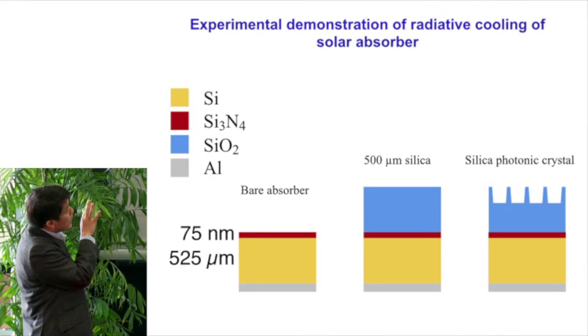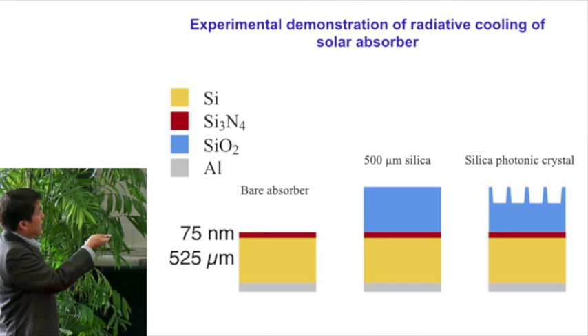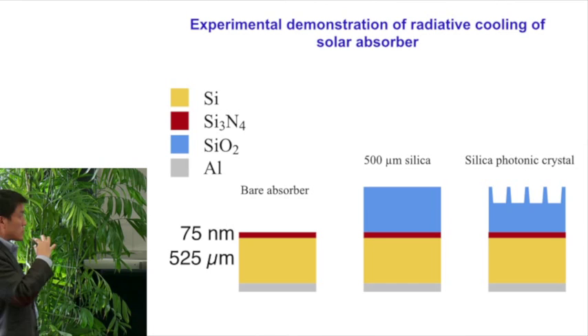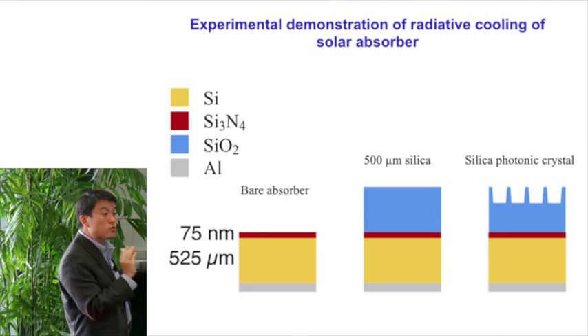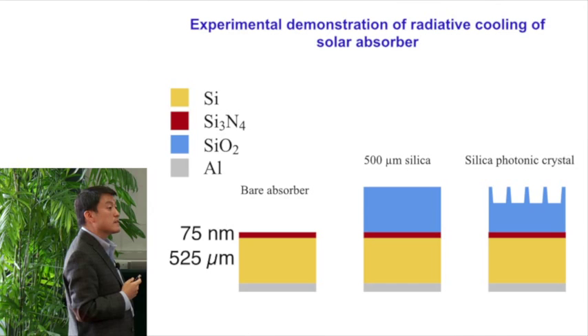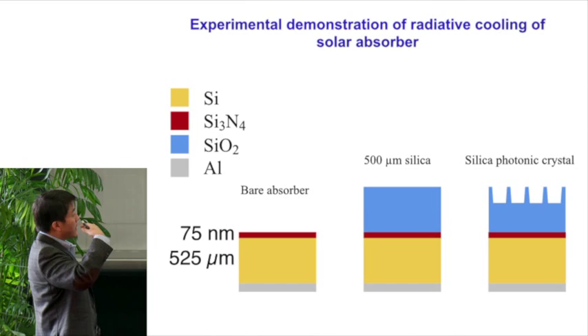So we start with a bare silicon wafer. These are wafers that are typically used as a starting point for solar cells. Then for cooling purposes, we compare this to two different structures. One of them has a thick layer of silica, about a 500 micron thick silica layer. This is partially to simulate, because in an actual solar cell structure, there will be a thick silica layer on top. So this is partially to simulate that.